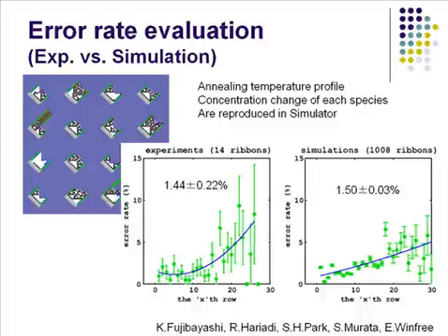And also in the real tube experiment, we have some spurious nucleation of the tiles, which is not initiated by the origami structure. So that kind of error absorbs the tiles, and that destroys the constant balance between the DNA tiles. That makes the error rate worse.